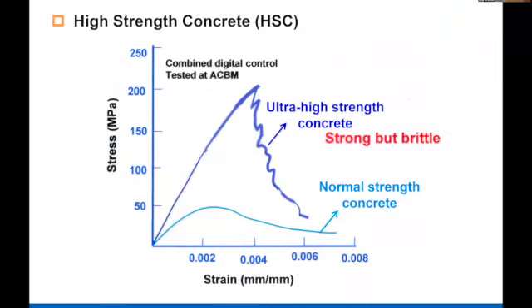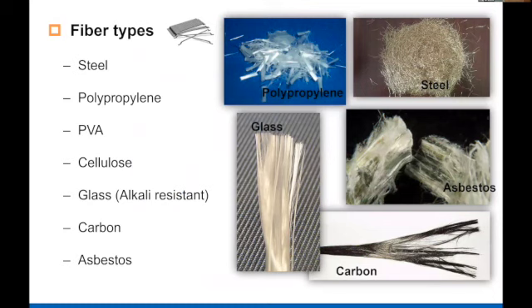Here I've shown the stress strain curve when you compress normal strength concrete, which is about 50 megapascal here, and what we now call ultra high strength concrete, which is 200 megapascal. You can see that it's possible to get a stable response. But after the post peak, you can see ultra high strength concrete is almost like glass, vertical. So it's very, very brittle. It doesn't have what we call the strain softening response of normal concrete. So in order to use ultra high strength, we have to reduce the brittleness or increase the toughness. And currently, the main way we do it is by introducing fibers.